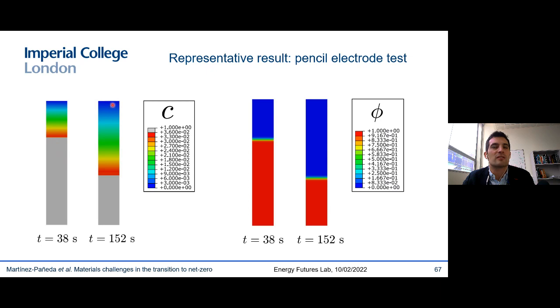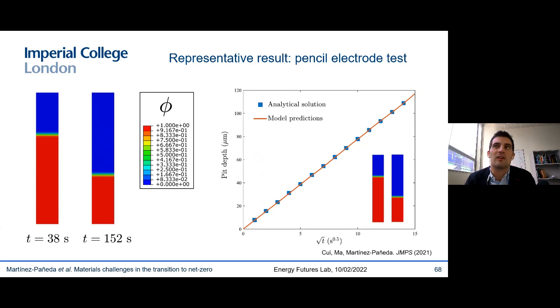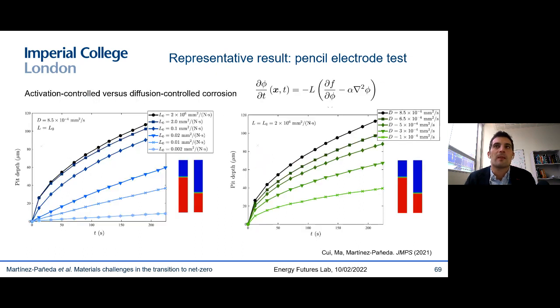So far away from the interface, at the edge of the electrolyte, the concentration of metal ions is 0, but it rises to the saturation concentration and eventually to a value of 1 inside of the metal, where there's no diffusion of metal ions. And you can see here the prediction compared with the analytical solution of the variation of the pit depth versus time, and you can see that we get a perfect agreement. And this shows how we can capture the competition between activation versus diffusion control corrosion, as we observe in the experiments. You can see on the left that if the corrosion current is small, then we see linear behavior, indicative of activation control corrosion.